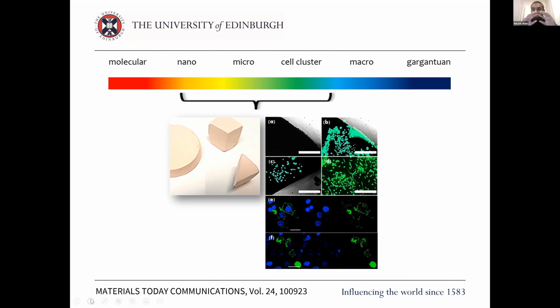Yeah, so they have really interesting corrugated surfaces, and cells really love topographically irregular surfaces. If you see cells growing well on a surface, it's often a topographically irregular surface, because the cell can actually cling. So if you have a fibroblast, it will form a star if it's healthy, whereas if it's not healthy, it'll form a ball. And what we found is, first off, we needed to make three-dimensional architectures from these diatoms.